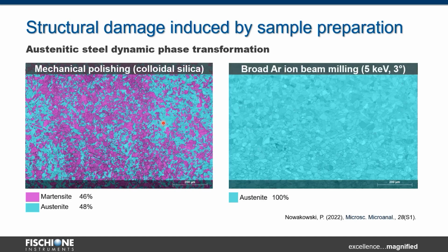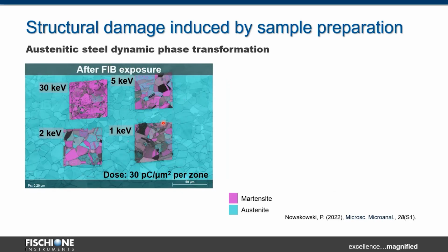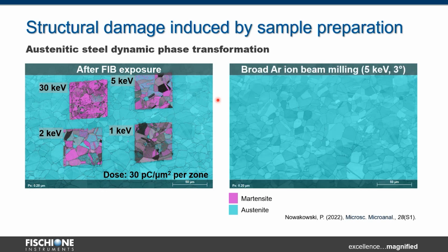If you use broad argon ion milling for that sample preparation, you will get 100% austenite and a clean, nice sample. And the same you can observe if you use FIB for your sample preparation: you will get that dynamic phase transformation, the austenite to martensite, and you will ask yourself what happens here. Nothing happens. You will just induce that transformation, it is an artifact, and you deal only with austenite. If you use argon ion milling in one of our systems, you will get a pristine, clear austenite sample after preparation.